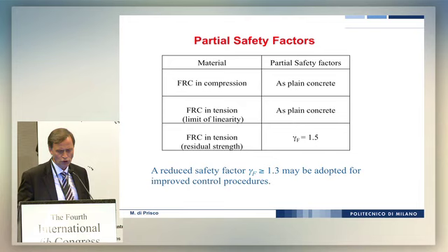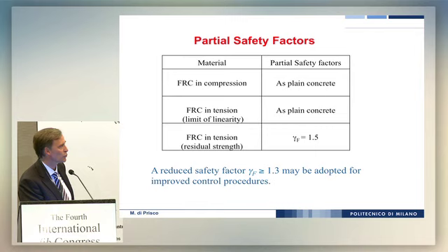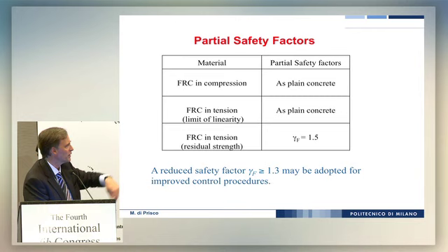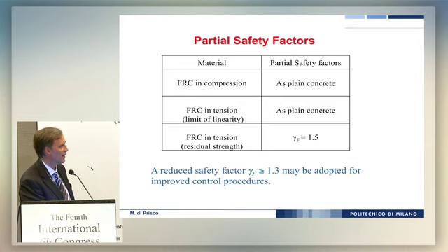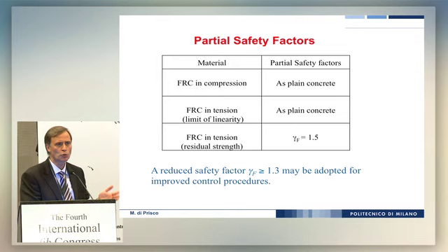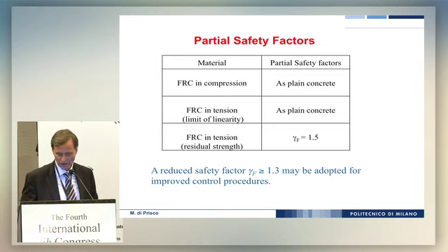Passing to the partial safety factor, we would like to emphasize that we conserve the same coefficient we have in concrete, in tension, and sometimes if you have an improved control procedure, that means, for instance, the use of structural specimens, so without notch, and so you produce exactly the same thickness, the same casting procedure, and so on, you can reduce such kind of safety coefficient.